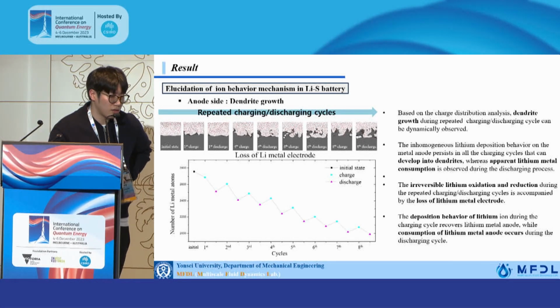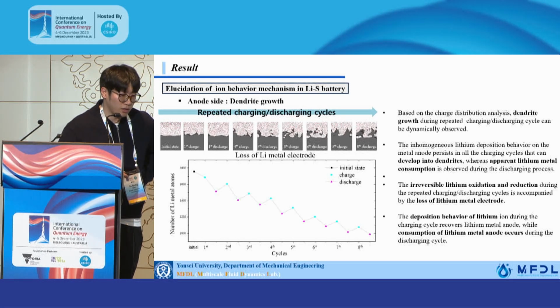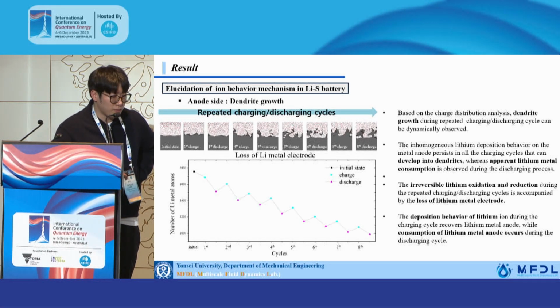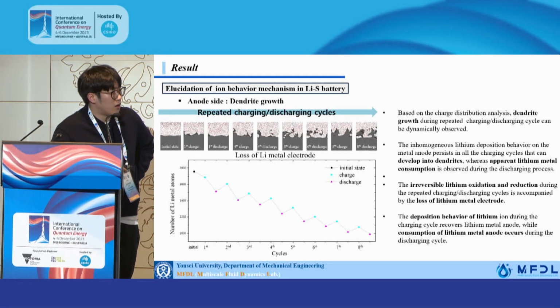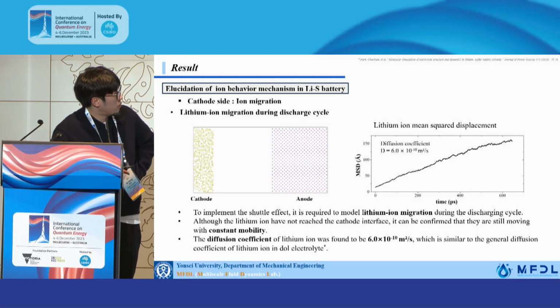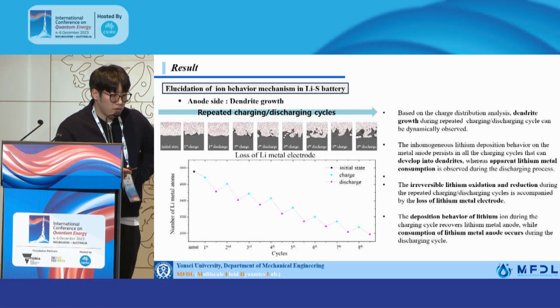And based on the charge distribution, the dendrite growth during the charging and discharge cycle can be observed. And because of the irreversible reaction during the repeated charging and discharge cycle, in the charge cycle, the oxidized lithium ion reduced on the anode lithium anode, and in the discharge cycle, the ion on the anode side oxidized to the electrolyte, and the electron consumption occurs.